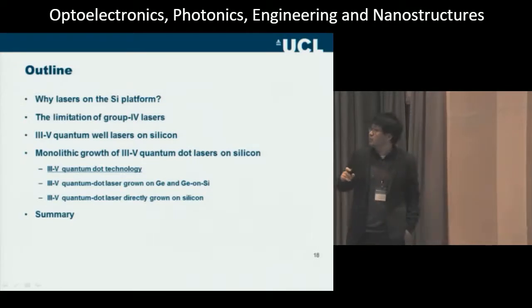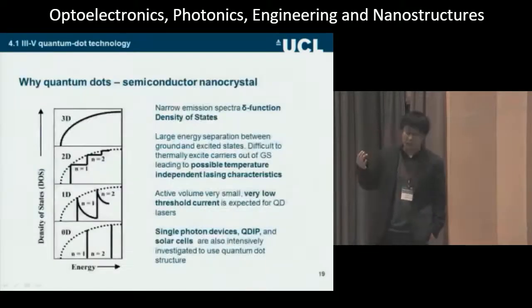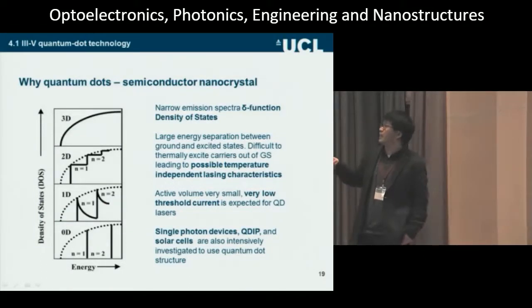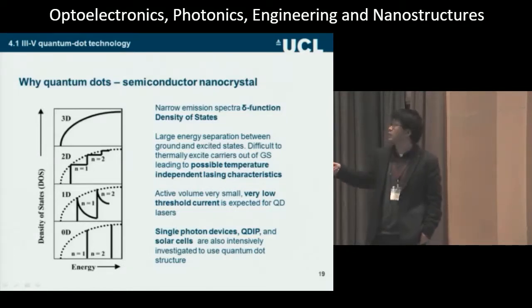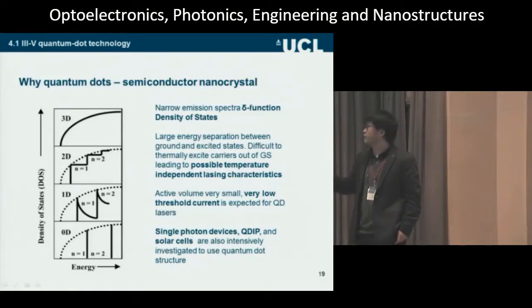About 10 years ago, I joined UCL, and we had one idea to put a quantum dot laser on silicon. Why quantum dots? I think it's the density of states. For quantum dots, you have a delta function density of states. Each energy level is separate. Because of the separate energy levels, you can get possible temperature-independent laser operation, and also very low threshold current density. Of course, you can make single photon devices and also solar cells and detectors. For us, we mainly focus on the laser part.